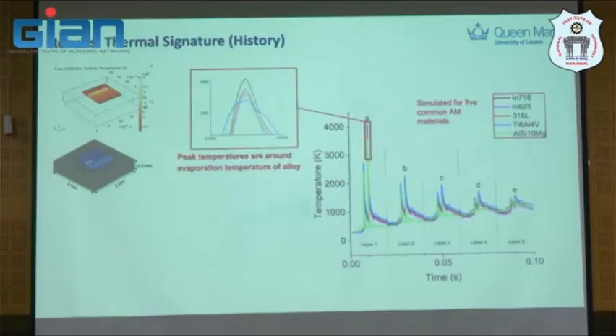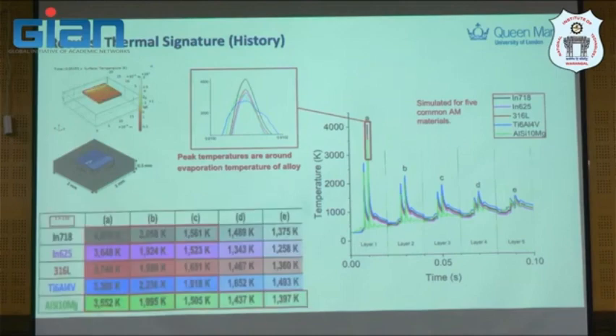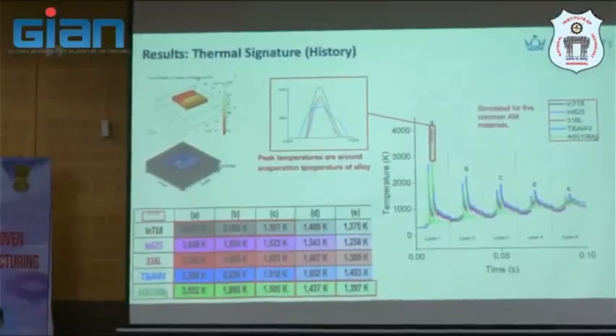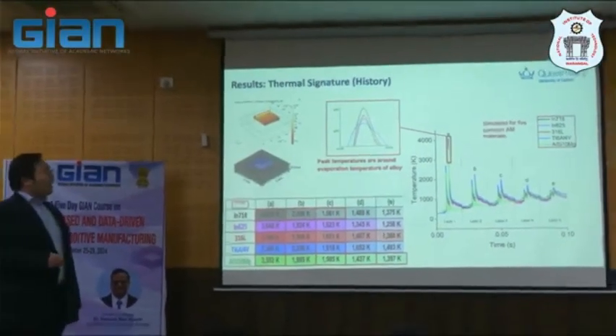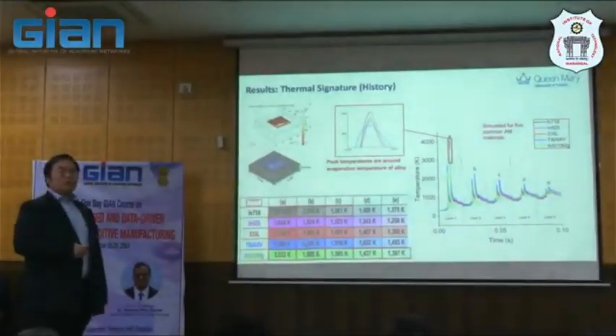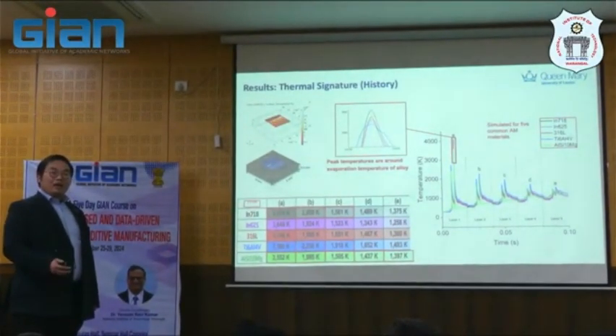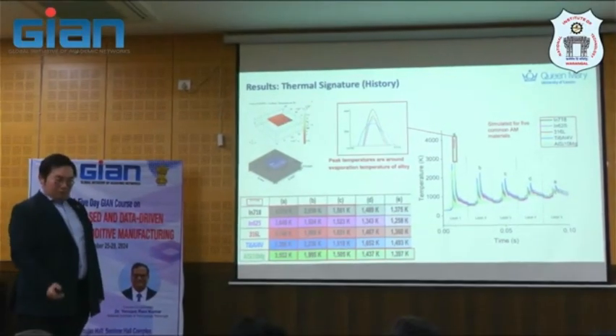And then if we try to understand the thermal signature a little bit, we build this 1 by 1 millimeter cube here, and we can extract the classic thermal signature for different layers here, for different materials as well. And the information from this is quite useful, and I will have some examples a bit later, saying that this peak temperature is important in so many possible ways that we can think of. But this is one example, one question that we can ask, that this model can tell us quickly how many layers beneath this material has been remelting.